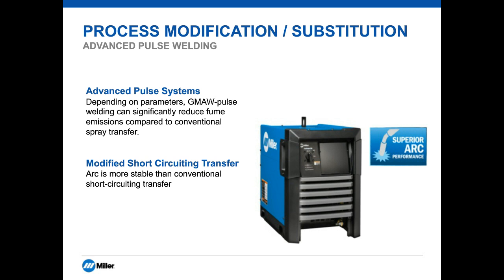As I mentioned earlier, the type of weld metal transfer can have a significant impact on fume generation. Modified short-circuiting transfer provides a more stable arc than conventional short-circuiting transfer, which can help to reduce fumes. It has also been found that switching from conventional spray transfer to pulse transfer when gas metal arc welding can significantly reduce welding fume generation.